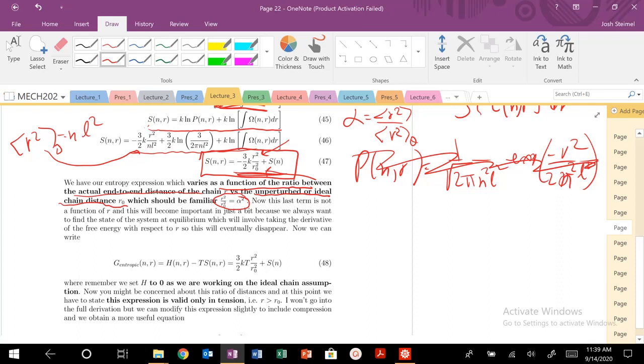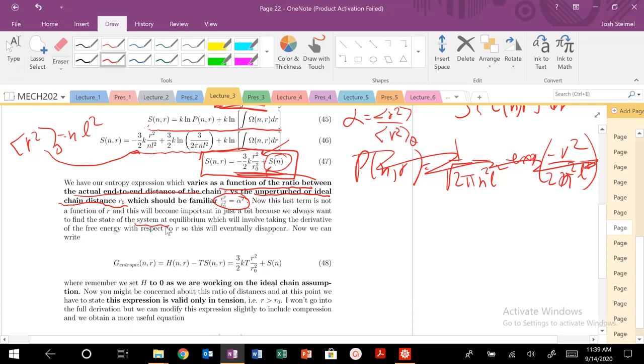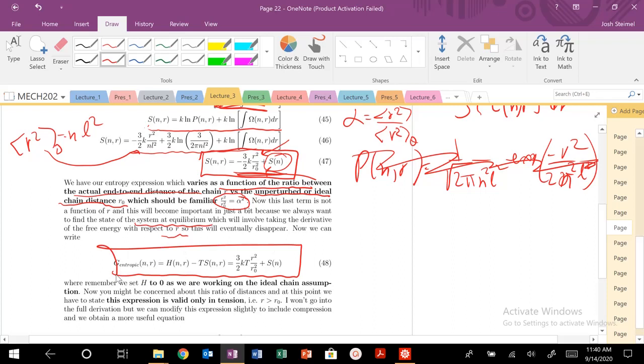What about the S-sub-N term? It also varies as a function of N, but when we deal with free energies and find the equilibrium state of the system, we take the derivative with respect to R — so that term drops out. Now, the free energy of the entropic component has H equal to zero because we're working with the ideal chain assumption. We're not worried about monomer-monomer interactions that deviate from zero. The only thing happening in the entropic component is that we're going from an ideal coiled state and extending it, producing that restoring force.